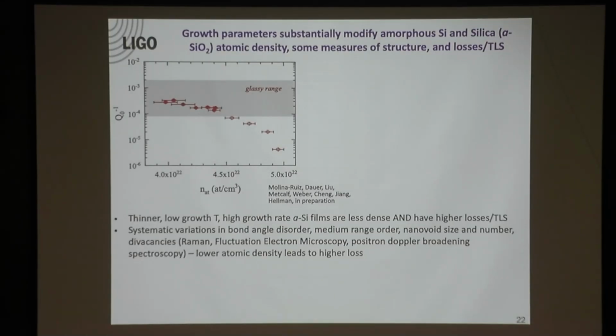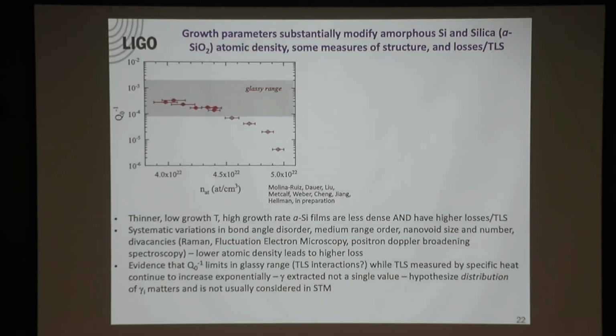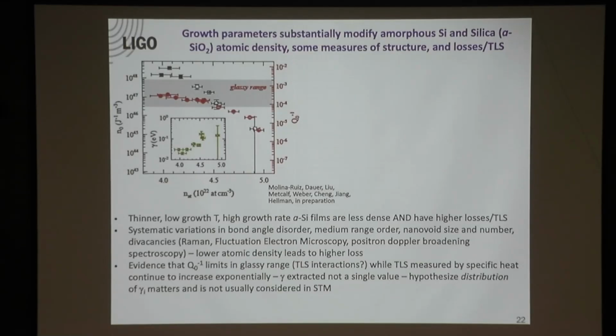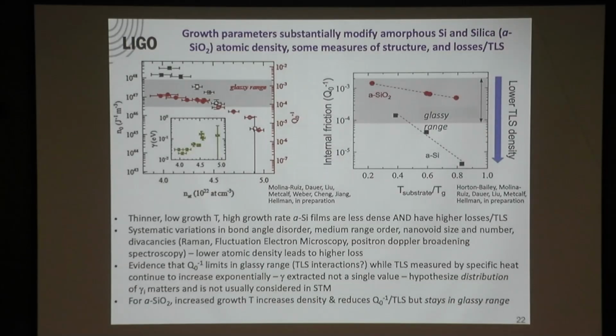and that stops them from continuing to grow. And just as a tantalizing other feature, I'm going to put the heat capacity on here. I haven't talked about heat capacity at all, but the heat capacity is another way of getting at these tunneling level states. The red is still that Q. The heat capacity just keeps going up. So we believe we're heading toward an improved version of the standard tunneling model that is going to enable us to say the states themselves continue to increase, but it's their interactions that cause them to limit in this range. Okay, and then I'll just leave you with the fact that for LIGO, it's great that we understand this. They don't really care that much that we understand this; they really care that we find materials that can work.